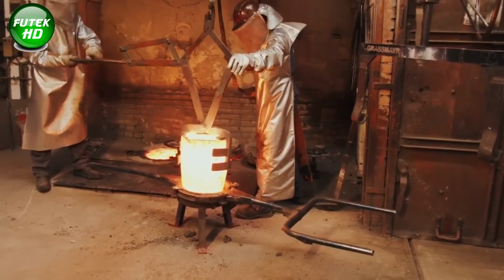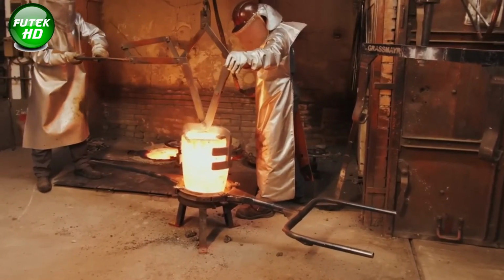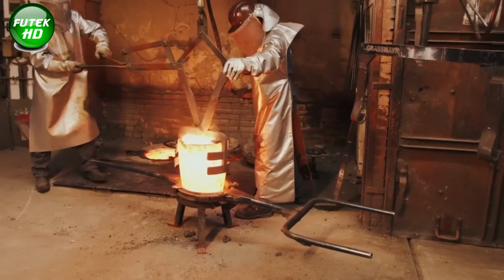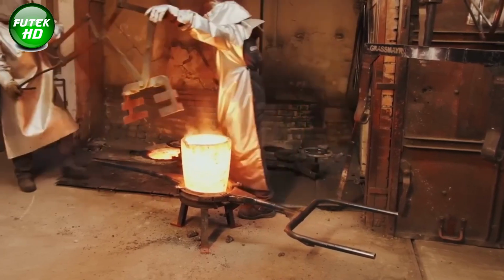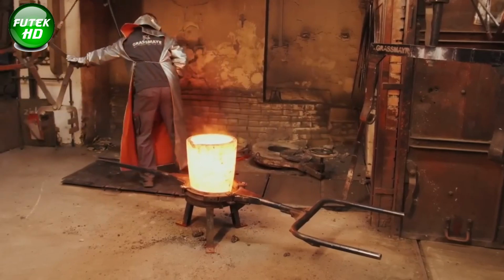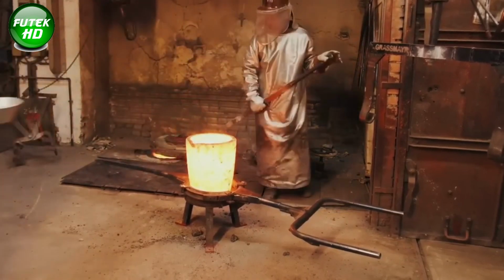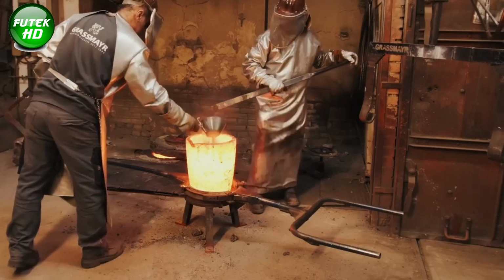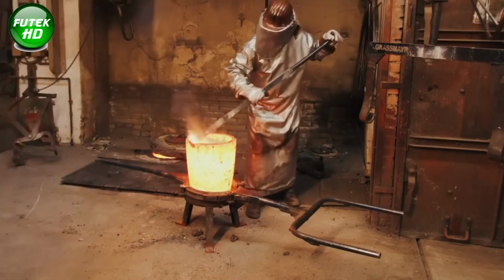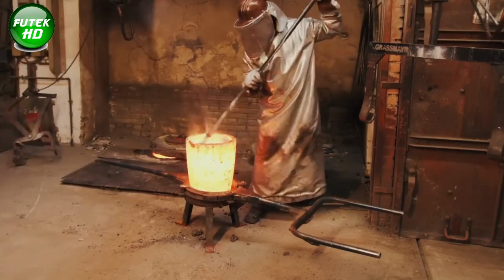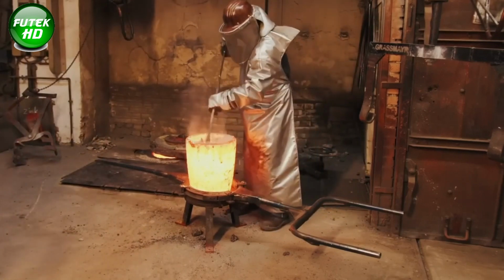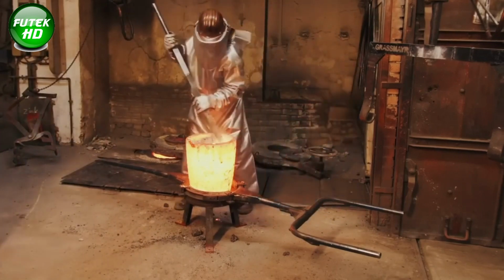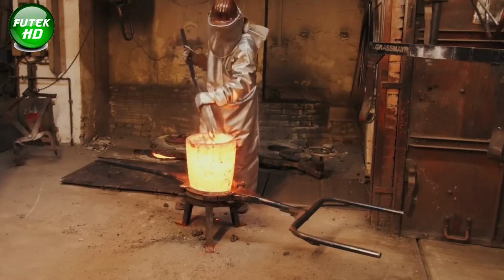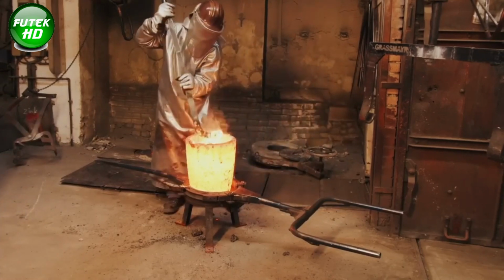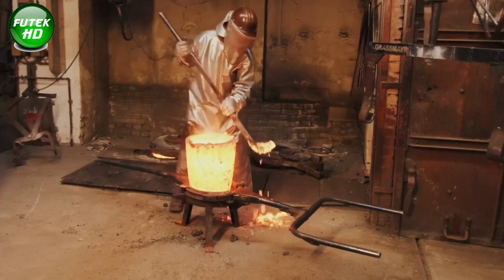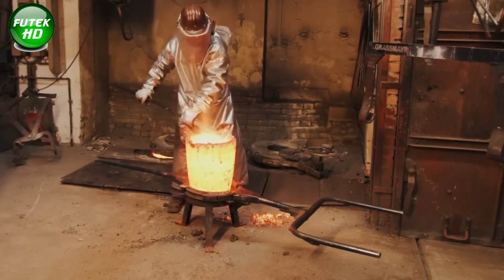The bell casting process at Grassmayr Bell Foundry includes meticulous preparations before pouring the molten metal. One critical step is preheating the molds. This procedure is essential to prevent thermal shock, which can occur if hot metal is poured into a cold mold. Thermal shock can cause cracks and other structural defects in the bell, compromising its integrity and sound quality. By preheating the molds, the foundry ensures a more gradual and controlled transition of temperatures, promoting a smooth casting process.